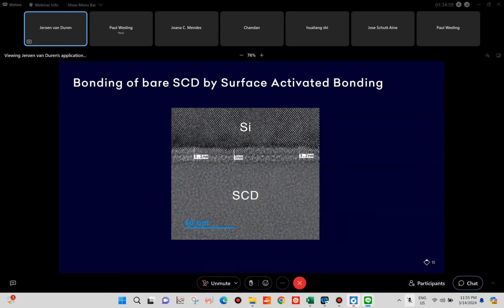Now, to give an example of bonding diamond to silicon without metallization, here you see a TEM image of diamond bonded to silicon by surface activated bonding. Now, the fact that you have to use a TEM already tells you that there is barely a bond line thickness. You see a little bit of amorphization at the interface of a few nanometers. And that's obviously very important, that you can get the diamond very close to the hotspot without a thermal interface material, because the more effective the diamond is in its heat spreading. To give you a sense, these pull strengths are really high, like 80 megapascal. Thermal resistance is very, very low. It's like 1,000 times lower than a typical high-end TIM.